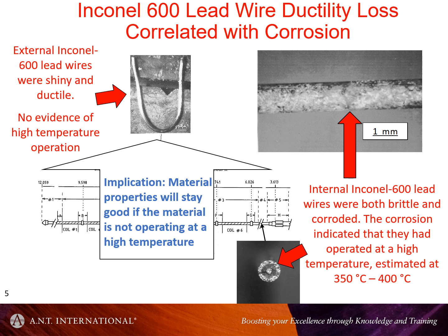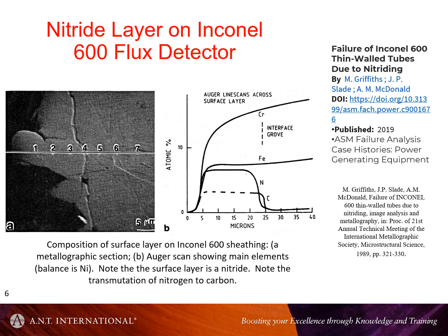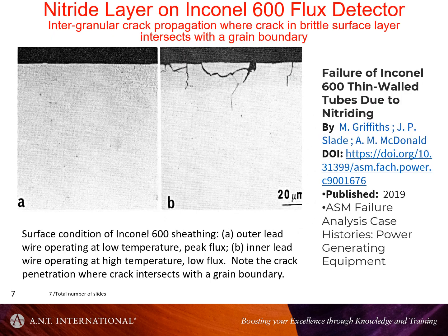So the implications were the material properties would stay good if it were not operating at a high temperature. I mentioned there was a corrosion layer on these detector components, the Inconel 600 in this case, where they were hot, and it was a very high nitrogen layer, so you're reacting with the nitrogen in the air. And what was interesting is also this carbon layer mixed in there, and that comes from the transmutation of the nitrogen to carbon. So one of the things that was clear is where the properties were bad, where these things were very brittle, there was this thick layer.